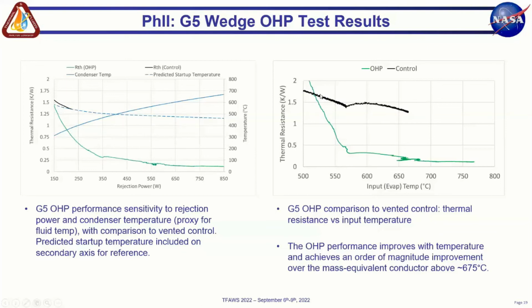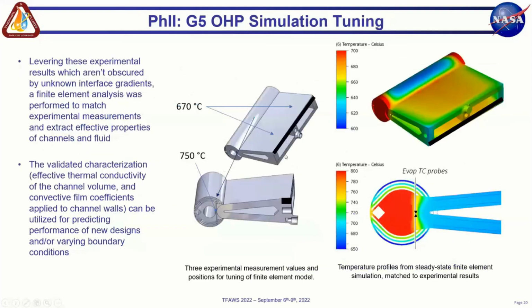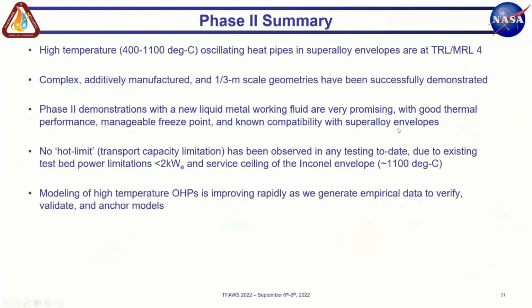Again, on the right, we have a comparison of the mass equivalent control thermal resistance to the OHP, and about an order of magnitude spread here. So we took these experimental results back into the simulation environment and essentially just turned the knobs we have in the finite element environment to match experiment. Then we can extract the thermal characterization of both the channel volume and the convective film coefficients applied to the walls, and utilize that for predicting performance of other designs and varying boundary conditions.